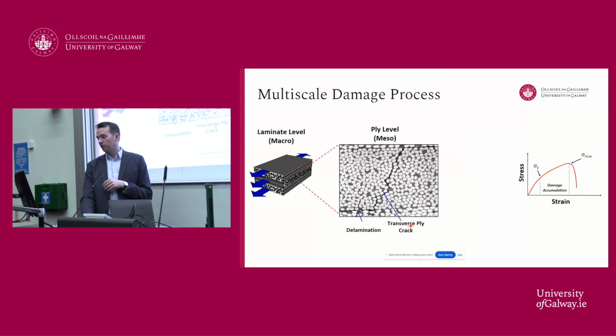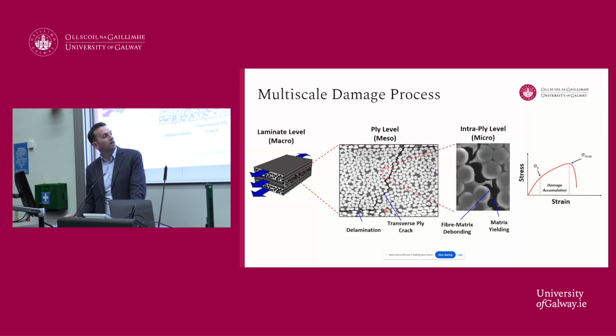If you look at these types of materials in more detail, at the ply level, here we're looking at a transverse cross-section. The circles are your carbon fibers coming out of the page, and the darker material is the polymer matrix. You'll start to see things like transverse ply cracks, which start from debonding between fibers. In this material, the fibers are about 7 to 10 microns in diameter.